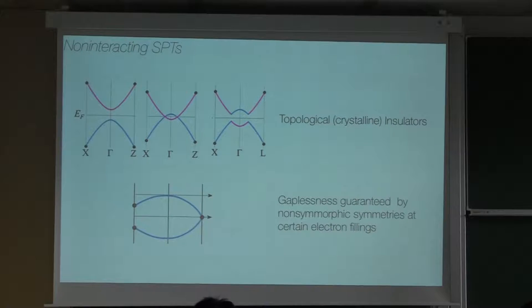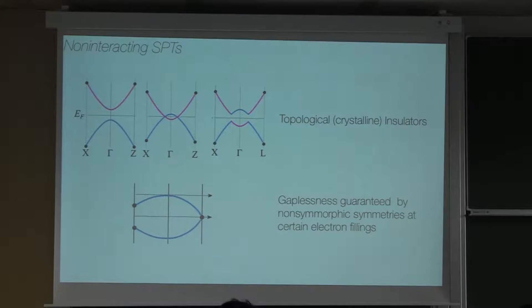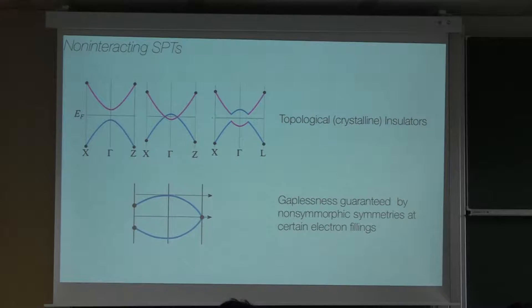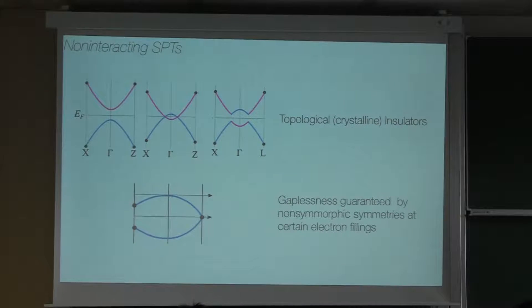These things are called symmetry-protected because, for example, in the topological insulator you need at least a Kramers degeneracy from time reversal. You can also have topological crystalline insulators where space group symmetries provide this protection. And really recently, in the last one and a half to two years, we have rediscovered a new type of symmetry — non-symmorphic symmetries. I'm sure Andre will talk about this more later. All known topological insulators or crystalline insulators are basically materials that have symmorphic symmetries.